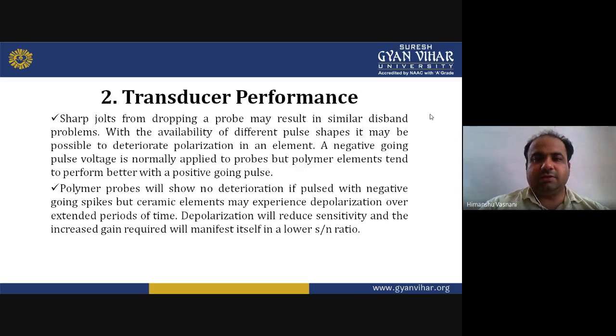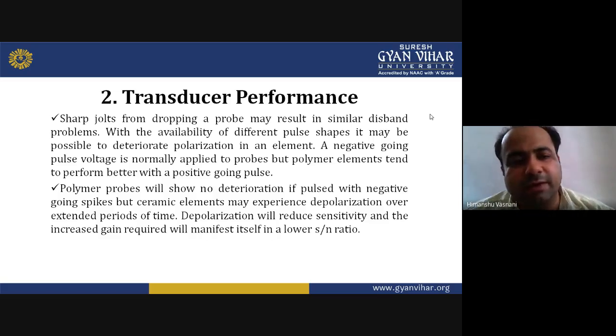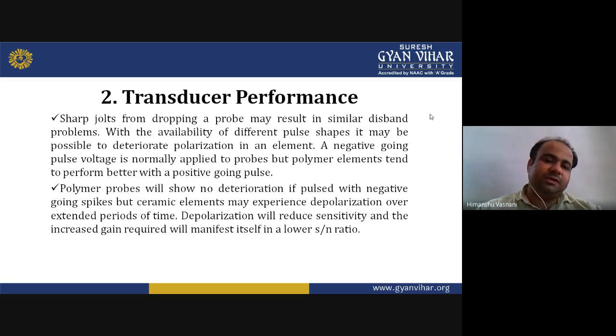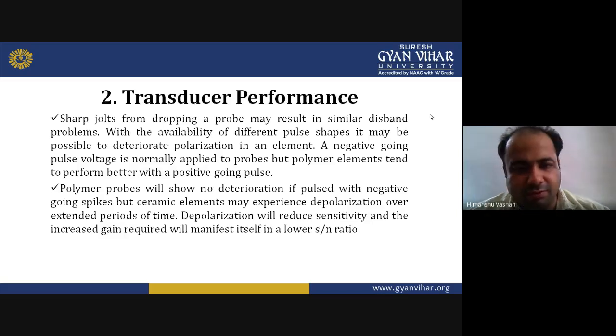Now the transducer performance. The sharp jolts from dropping a probe may result in some error. It may be possible to deteriorate the polarization of an element. A negative going pulse voltage is normally applied to probes, but polymer elements tend to perform better with a positive going pulse. So polymer probes will show no deterioration if pulsed with negative going spikes.